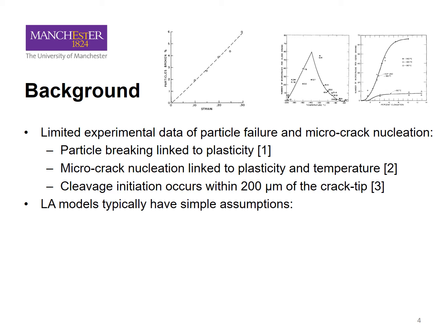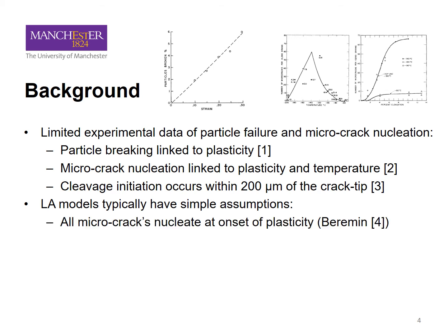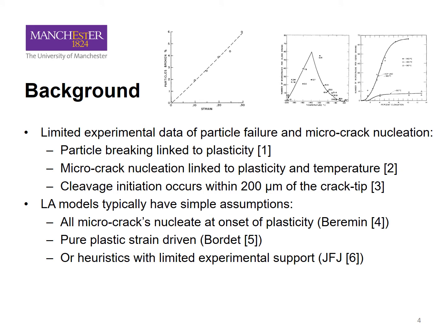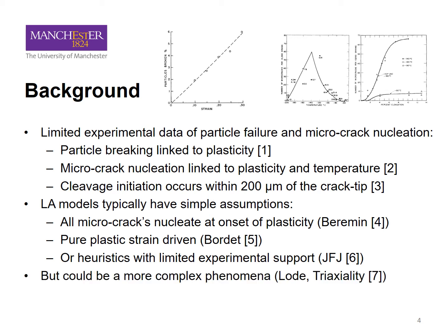Now, local approach models typically have simple assumptions. They either assume that all microcracks nucleate at the onset of plasticity, such as in the Beremin model, or there's a gradual creation of microcracks, more in line with what Gurland showed in the Bordet model, or there's sometimes heuristics which have limited experimental support, such as in the JFJ model, where nucleation is linked to the energy density in the strain in the plane normal to the maximum principal stress.